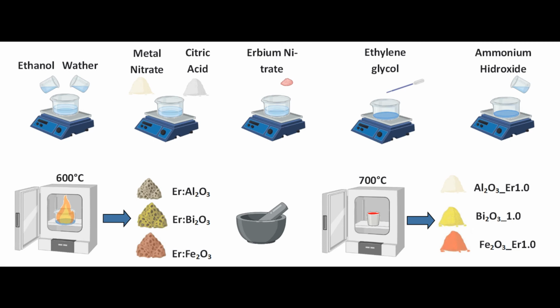The synthesis was made by a modified Pechini method, in a one-to-one aqueous solution of water and ethanol in which a 2 to 1 molar ratio of citric acid and the corresponding metal nitrate, iron, bismuth, and aluminium, were added, followed by erbium nitrate for a concentration of 1% molar. After evaporating the ethanol, 1 milliliter of ethylene glycol and 5 milliliters of ammonium hydroxide were added to form a solid gel at 170 Celsius degrees.